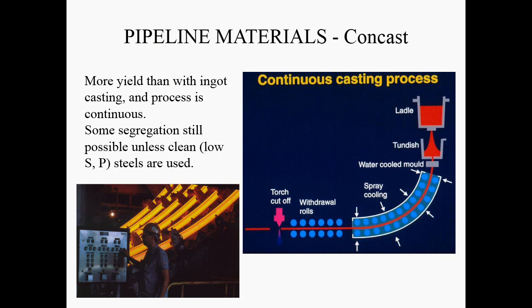We can control the thickness by controlling the speed of these withdrawal rollers, which are pulling it, and the guide rollers here. We can control the cooling rates by spraying water onto these systems, and we can control the lengths of the product and the thickness of the product by the rate at which we pull things out. And then we've got a torch just to cut it off at the end. So we're producing by one process with a constant set of process parameters a product form which comes out, and if it's a strip will come out, be coiled up, and then the coil will be sent off for subsequent processing at a part of the steelworks that makes product form. So the pipe mill, for instance.